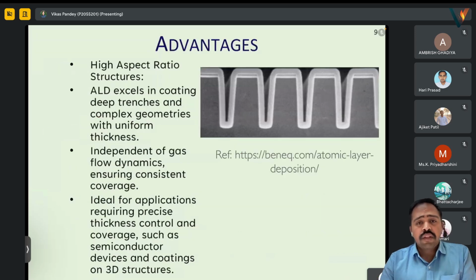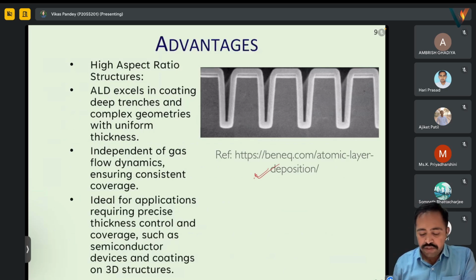So what are the advantages? This is taken from a website of a company that makes ALD systems, and they have provided some images. You see, if it was a CVD system, and the scale here is actually quite low, I forgot to put the scale here. It's quite low, in terms of microns, and sometimes even in nano. If you see the coverage, it is almost the same thickness here as on the side walls, which is not possible when we are doing a CVD or PVD process in general.